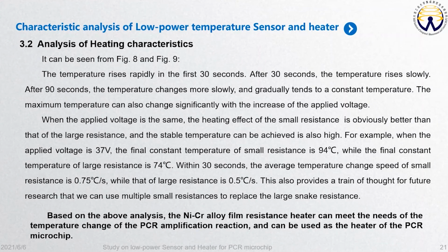It can be seen from Figure 8 and Figure 9 that the temperature rises rapidly in the first 30 seconds, and after the 30 seconds, the temperature rises slowly. After 90 seconds, the temperature changes more slowly and gradually tends to a constant value. Based on the above analysis, the nickel chromium alloy film resistance heater can meet the needs of the temperature change of the PCR amplification reaction and can be used as the heater of the PCR microchip.